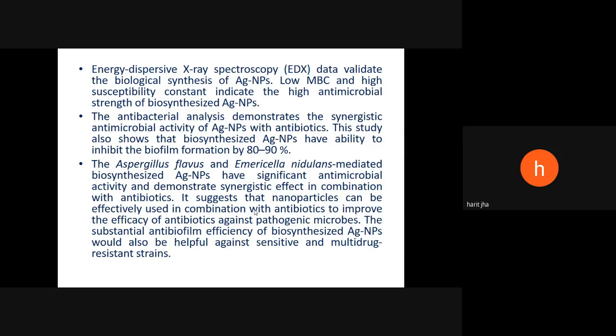So we also found that the silver nanoparticles can show a synergistic effect with the antibiotics, and the A. flavus and Emericella nidulans mediated biosynthesized silver nanoparticles had significant antimicrobial activity and demonstrate synergistic effect in combination with antibiotics. It suggests that nanoparticles can be effectively used in combination with antibiotics to improve the efficacy of antibiotics against pathogenic microbes. The substantial anti-biofilm efficiency of biosynthesized silver nanoparticles can also be helpful against sensitive and multi-drug resistant strains.